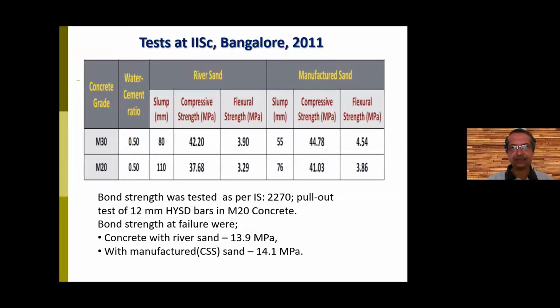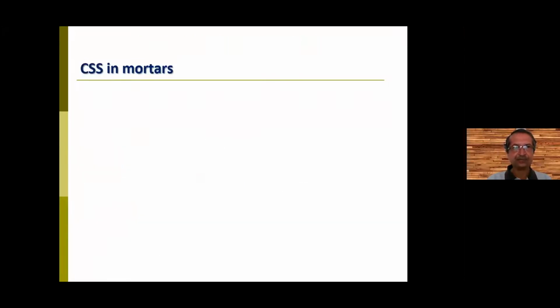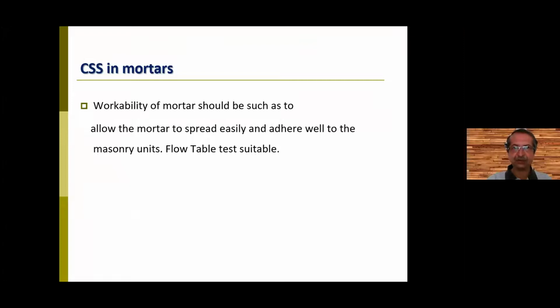So this is a test which was done long back, around 10 years back at Indian Institute of Science. You can see that between the river sand and manufactured sand, the manufactured sand slump may be slightly less, but the compressive strength and flexural strength are better than the concrete made by river sand. Bond strength was good, and it was also checked for mortar. So the workability of mortar is the most important thing here, and it should be such as to allow mortar to spread easily and adhere well to the masonry units, and a flow test is good enough for you.